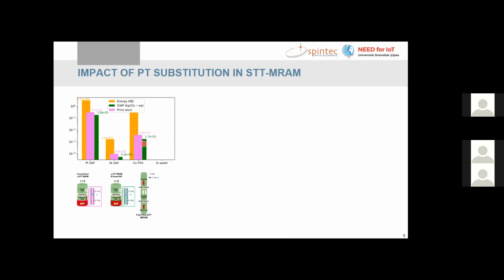We are also studying another alternative that is based on perpendicular shape anisotropy, and even with this other alternative, even if we use more material because we have a thicker structure, at the end we also have reductions because we can have materials that are less environmentally harmful. But the point is that if we go to the big picture and see the requirements for the silicon wafer production, and this goes in line with our previous question as well, the requirements are relatively bigger, so that at the end, the substitution in these economical terms is not that important, I would say.